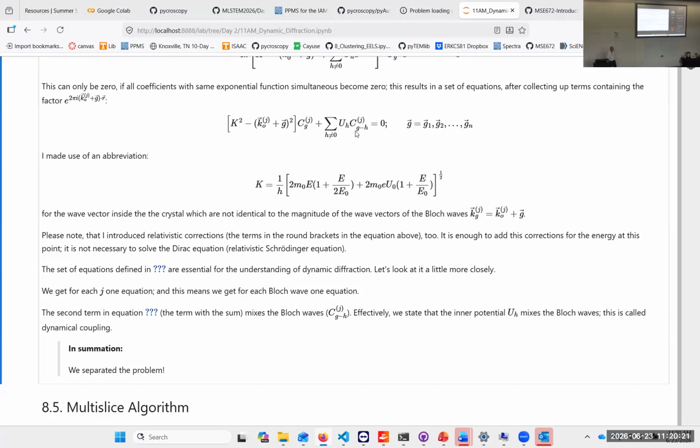So what you try to do is you go into the exact Bragg condition. We tilt, right? The Ewald sphere hits only two of these Bragg spots, and then we have two strongly excited beams. When we hit the surface of our sample, we have only the zero beam, and that is strongly excited. It's a pendulum, an oscillator. As we go through the sample, it looks like we have two pendula.